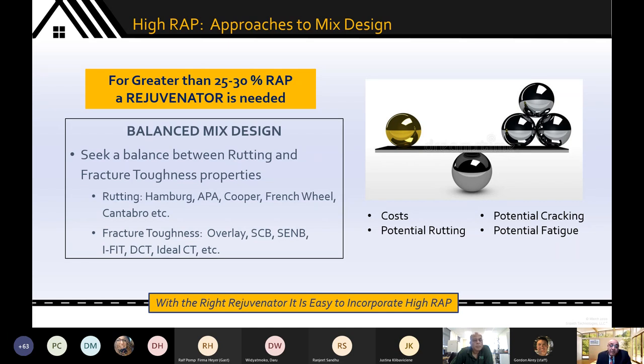So basically, it's pick one property from one test from column A, one test from column B, and we'll walk through some examples as to what that really means. Column A is rutting. You're looking at any one of these tests, the Hamburg test, the APA test, the French rut wheel test, the Cooper, even the Cantabro works. Fracture toughness, any number of different tests, Texas overlay is a fatigue type test, SCB, semicircular beam bend, SENB, single edge notched beam bending, and like that you have IFIT, DCT, ideal CT, sometimes even Marshall stability and flow have been incorporated here. Really, it's an alphabet soup. And it depends on what your lab is set up for, what your prior history demonstrates.